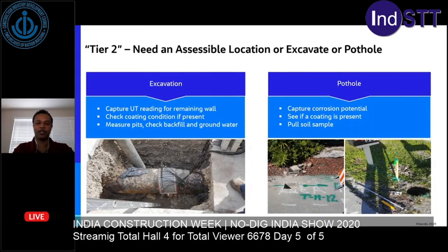And tier 2. In case you don't have that vault or that manhole accessible, you may have to excavate a pothole. So at an excavation, you can actually capture a UT reading for the remaining wall thickness. You can check to see if there's a coating present in case your as-built wasn't available. And also you can measure those pits with a pit depth gauge. You can check that backfill to see what the pH is, maybe send a backfill off for analysis to see how corrosive it is, maybe with chlorides or sulfates. And also you can check for redox potential, as well as groundwater influence. And you can see on that picture below the letter there is some groundwater intrusion at that excavation.